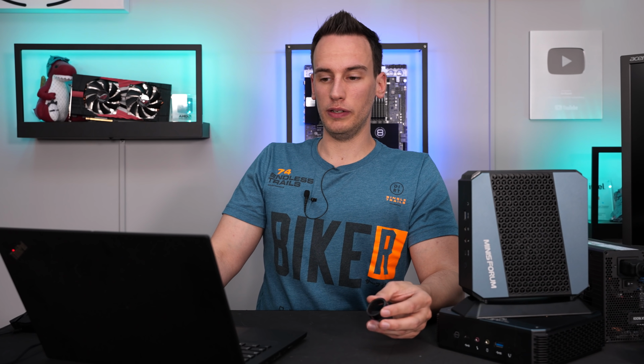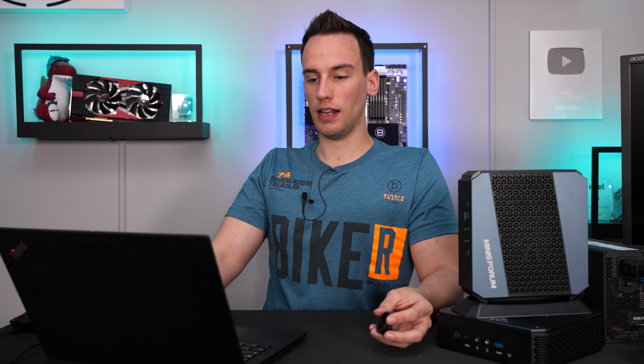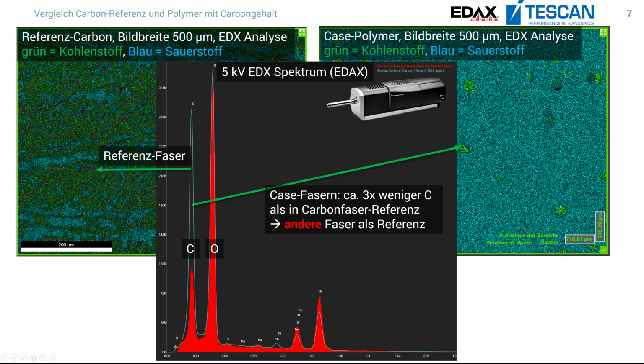And this is confirmed if we switch to the EDX analysis. On the left side, we have a ton of those green spots, and the green spots mark carbon or the carbon fibers, and everything that is marked blue is oxygen, which indicates that it's the polymer. Especially if we switch to the right side, you can see not that much green, not that much carbon, and a lot of blue stuff. It indicates we don't have that much carbon inside the polymer.